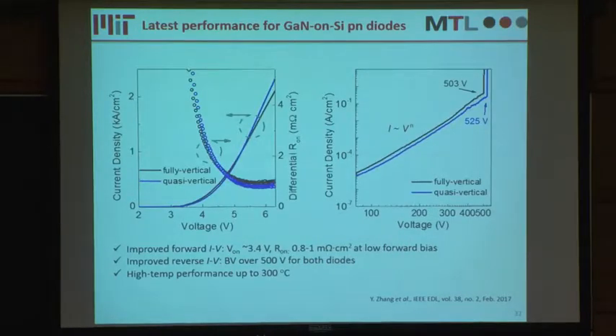So after all these optimizations, let's see what is the latest performance. In the forward characteristics, now the on-resistance is about 0.8 to 1, compared to 6 to 10 in our first generation device. This is almost one order of magnitude improvement.